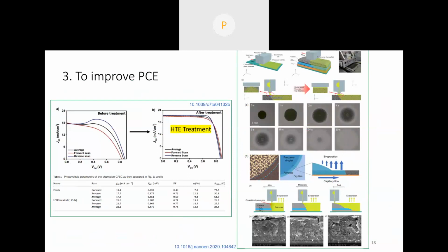Yeah. Now, to improve the photo conversion efficiency, there is one more problem with carbon-based solar cells: when you check the device performance, you need to soak light for a longer time, because the thickness of the structure is very high, and your perovskite thickness is also very high. So it takes time to get better efficiency. To improve that, for a faster response, we don't need to do light soaking for a longer time.